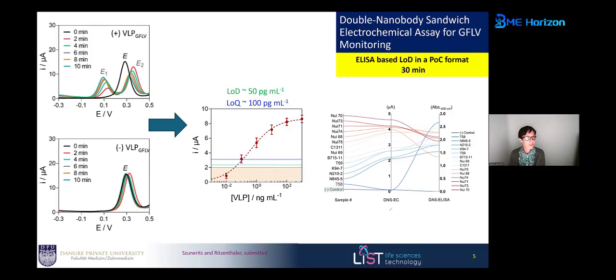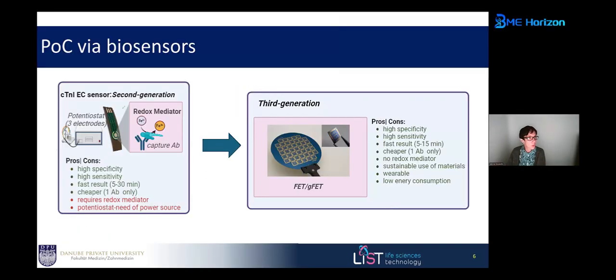Now there could be a variety of speculation as to why this is happening. It might be that the nanobody we are using does not interact specifically towards this, or it might be a human issue, that when we were grinding the leaves, we lost the particles. We don't know. However, there seems to be a very nice correlation between ELISA and the electrochemical sensor, knowing that with the sensor we get signals in 2-3 minutes. So I hope I have convinced you that this second generation, as I call it, where we use redox labels for readout, is already an advantage compared to ELISA.